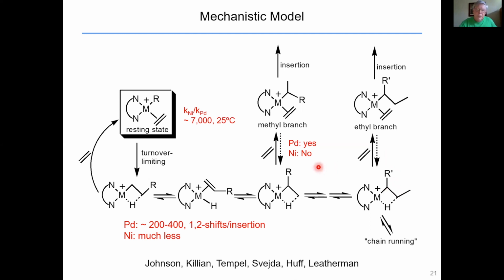In the case of palladium, this is reversible. And so even though it traps, it comes back to the agostic species and can run again, trapped, back out, and run again. And so what we find is that the palladium can walk over 200 to 400 carbons before it ever finishes off with an insertion process. So that's why you get these extremely branched materials.